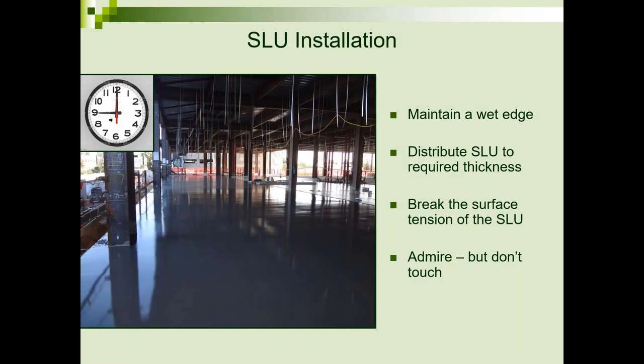Once you mix the product and apply it, you've got about 20 minutes of time to handle the product. You can see in the foreground, the surface is starting to lose its wet sheen or glaze. That product is beyond handling. And as you move forward, it's going to be more of a problem to correct any defects.